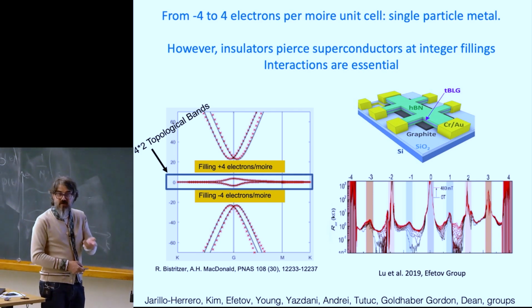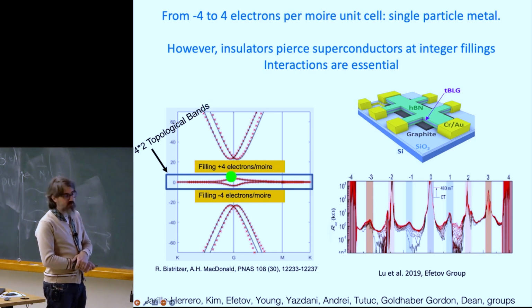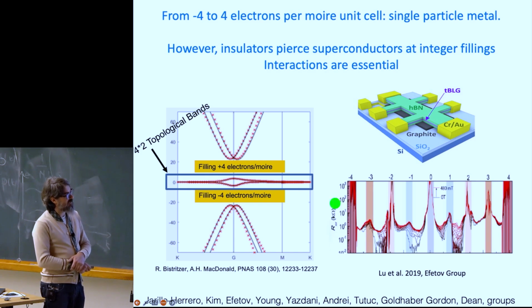It also has spin, with no spin-orbit coupling. Carbon atoms have 40 microelectron volt spin-orbit coupling, so we multiply it by another 2. So you have 2 times 2 times 2, that's 8 bands here. So I can fill them with 8 electrons per Moire unit cell. So we're going to count the filling in this gap. We're going to say it's minus 4 electrons. In this gap, we're going to say it's 4 electrons. So from here to here, I can add 8 electrons.